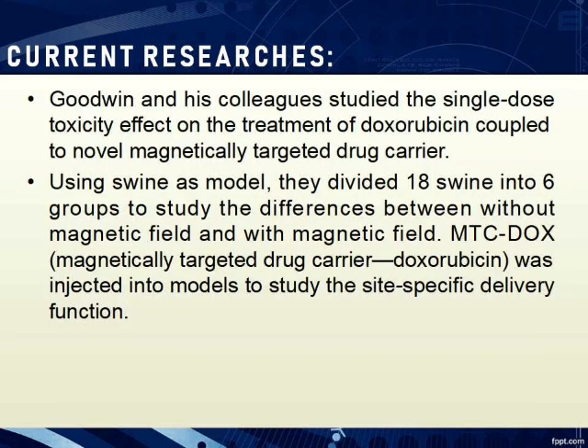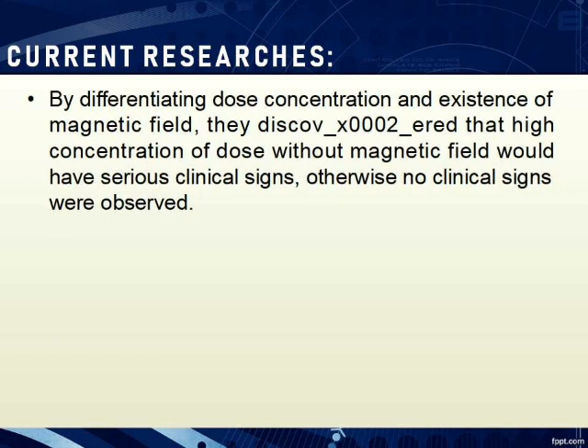In addition, Goodwin and his colleagues studied the single-dose toxicity effect on the treatment of doxorubicin coupled to a novel magnetically targeted drug carrier. Using swine as model, they divided 18 swine into 6 groups to study the differences between without magnetic field and with magnetic field. MTC-DOX, magnetically targeted drug carrier doxorubicin, was injected into models to study the site-specific delivery function. By differentiating dose concentration and existence of magnetic field, they discovered that high concentration without magnetic field would have serious clinical signs. Otherwise, no clinical signs were observed.